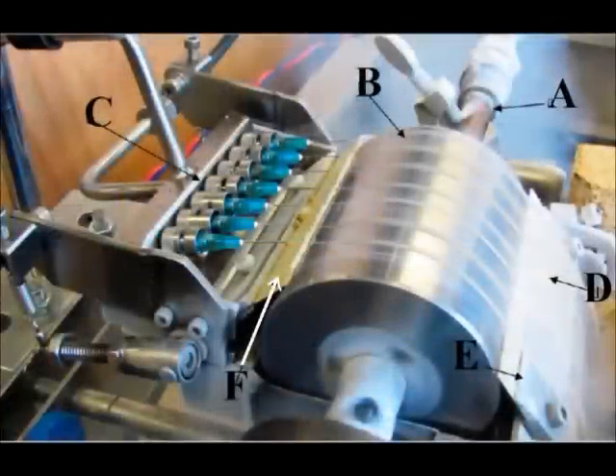The image shown is a rapid freezing device for lignin nanofiber production, depicting a lignin solution contacting the drum, freezing into continuous ribbons, and subsequently being collected in a cold storage vessel. A. Liquid nitrogen is delivered to the drum from a high-pressure tank at 1.4 megapascals to maintain the drum at the desired temperature, which is 77 degrees Kelvin. B. Steel drum is affixed to a variable speed motor, rotating at 300 RPM.